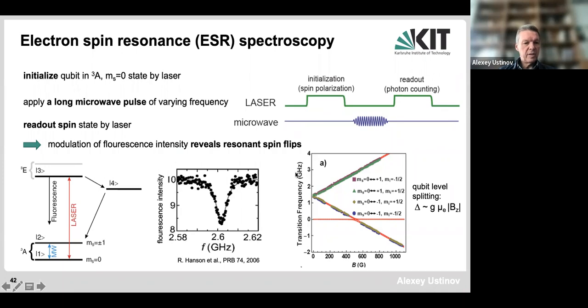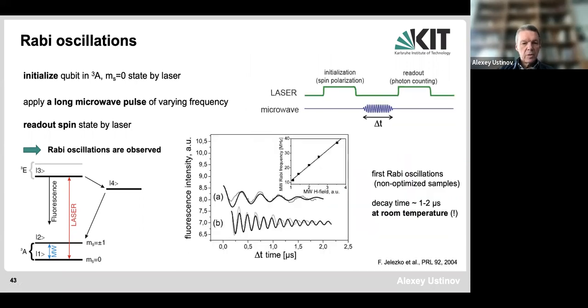So one can initialize the system by laser, then observe the occupation of the state by fluorescence. If you apply microwave, and you have this resonant laser as your measurement tool, then when you are occupying state 2, there will be no fluorescence, and if you occupy state 1, there will be fluorescence. This shows the line which is observed in the bulk ensemble of the NV centers, and it also shows the energy splitting depending on magnetic field, which shows the spin states associated with this kind of defect. So one can measure, of course, Rabi oscillations there and increase the intensity of the microwave field. You see this intensity of the microwave field is increased, and then the Rabi frequency increases. So this low frequency is A and high frequency is B.